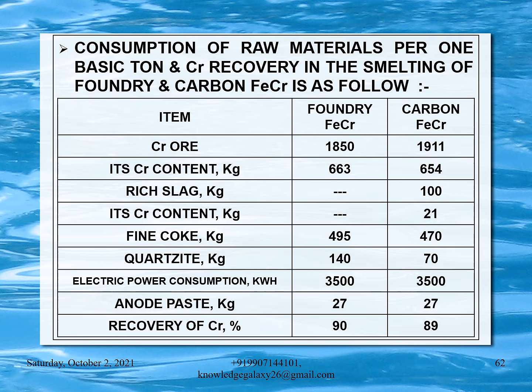Electric power consumption is 3500 kWh for foundry ferrochrome and 3500 kWh for carbon ferrochrome as well. Anode paste is 27 kg for both. Recovery of chromium is 90% for foundry ferrochrome and 89% for carbon ferrochrome.